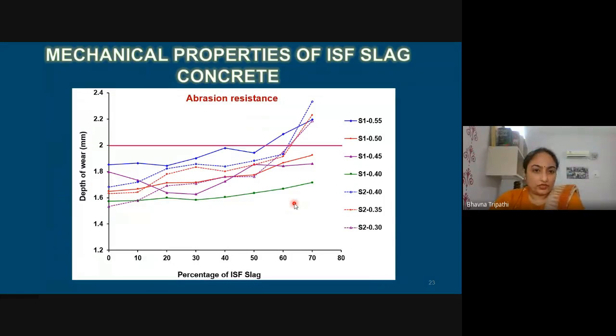Now, gradually moving towards other properties which are very much important for concrete to be applied in construction projects is abrasion resistance. The abrasion resistance of all these 56 mixes is presented here. And largely we can see that there are few specimens which have abrasion of more than, or we can say the depth of wear was more than 2 mm. Now, why this threshold line at 2 mm has been drawn is that as per IS 1237, there is one evaluation criteria that concrete having less than 2 mm wear can be used for preparing heavy duty floors or tiles used for heavy duty purposes.